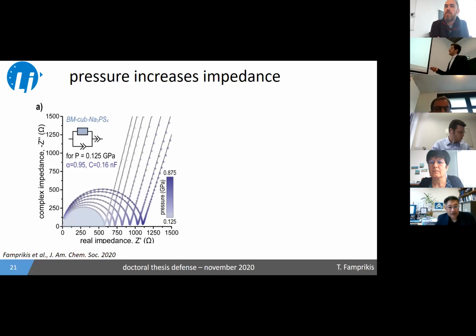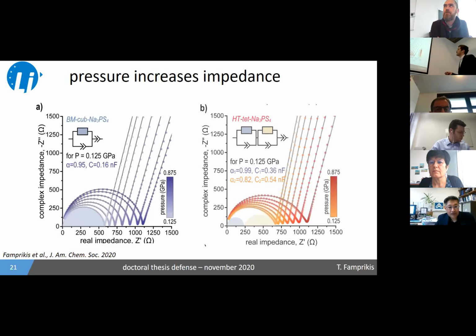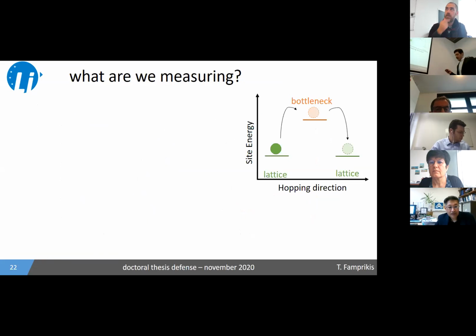I'm showing here the spectra as a function of pressure from the left to the right, increasing pressure and increasing impedance. So basically, the conductivity decreases as we apply pressure. This is for the ball mill sample, but we get something very similar for the solid state synthesized sample. But these are not very usual measurements, I understand. So let me very quickly try and capture the essence of what we are measuring here.